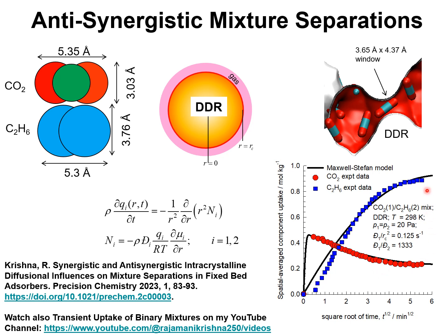So the mixture adsorption equilibrium favors C2H6, but the diffusion selectivity favors CO2, and we would like to cash in on the anti-synergy between adsorption and diffusion to achieve the separation of CO2 C2H6 mixtures in fixed bed adsorbers.